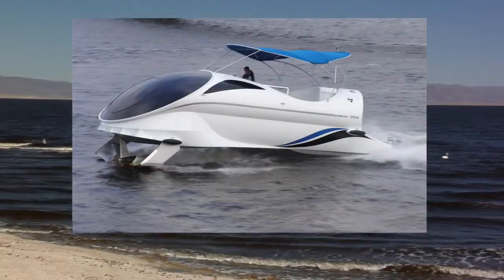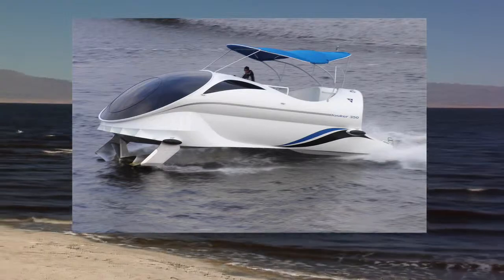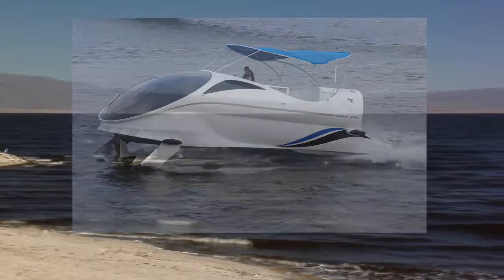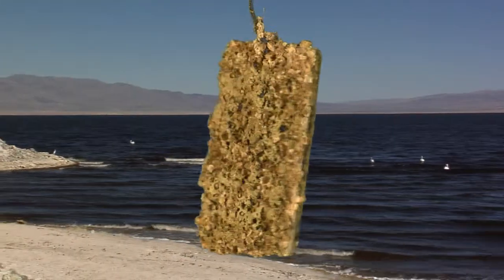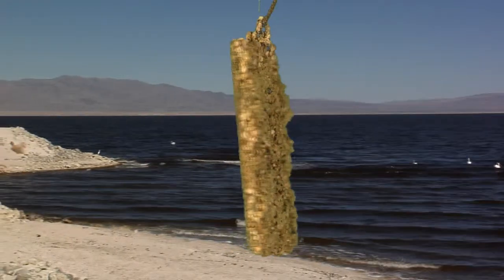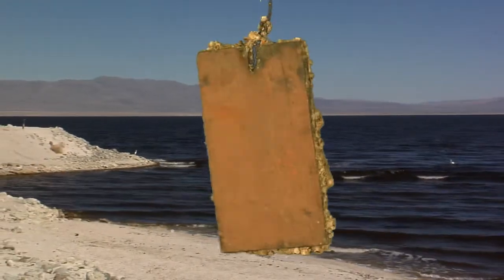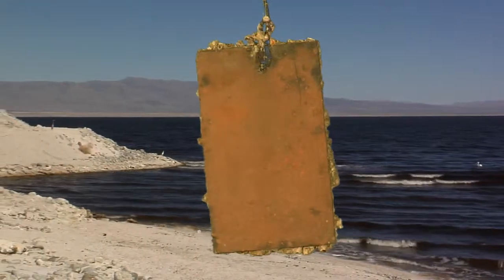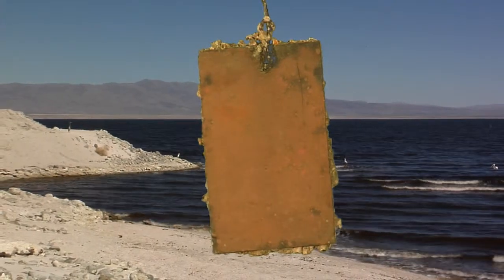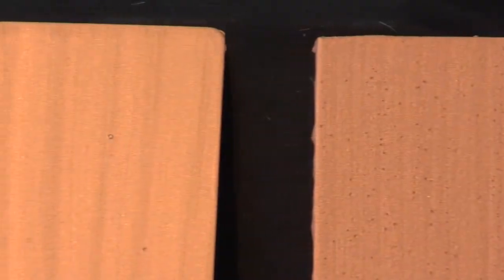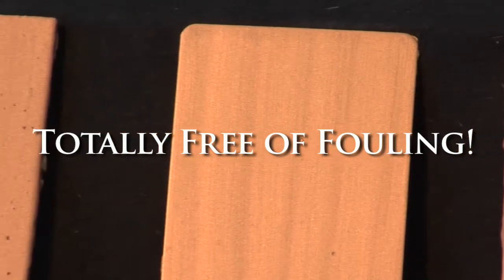Sweden. None of the panels treated with HyperCopper exhibited any growth after several months of exposure, while the uncoated side became severely encrusted with barnacles and marine growth. The copper flake coated bottom of the 50-foot boat in Sweden remained totally free of fouling.